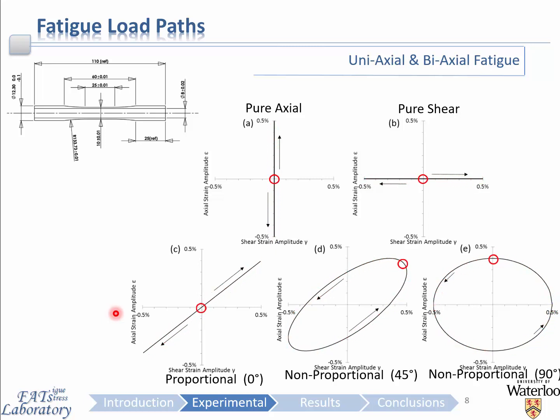Non-proportional loading, which effectively rotates the principal axes, can cause irreversible plastic deformation and damage on planes which were otherwise unaffected or inaccessible by the limited number of deformation mechanisms that Mg has available that I previously discussed. Once again, similar to many others doing work in multi-axial fatigue, we utilized a thin wall tubular specimen illustrated in the top left here, and 5 different loading paths: pure axial shown here, pure shear shown here, as well as a proportional axial and shear loading path here, as well as 2 non-proportional paths with a phase angle of 45 degrees shown here and 90 degrees shown here.